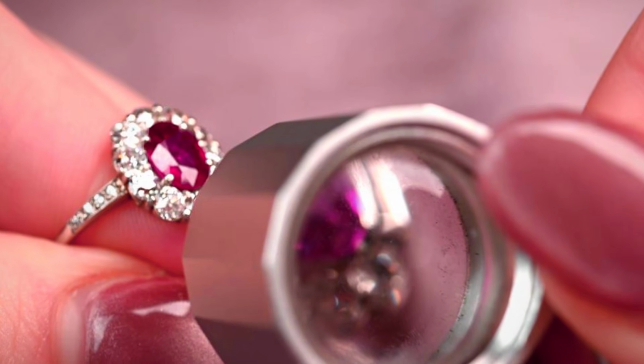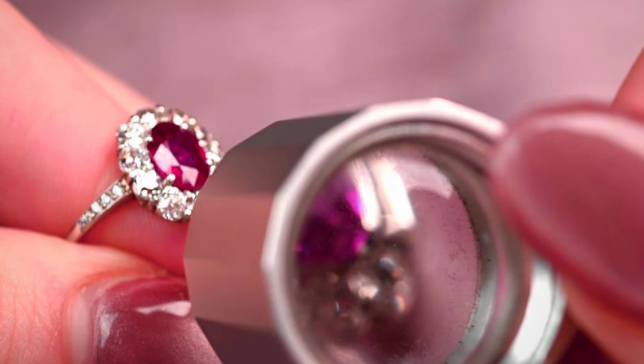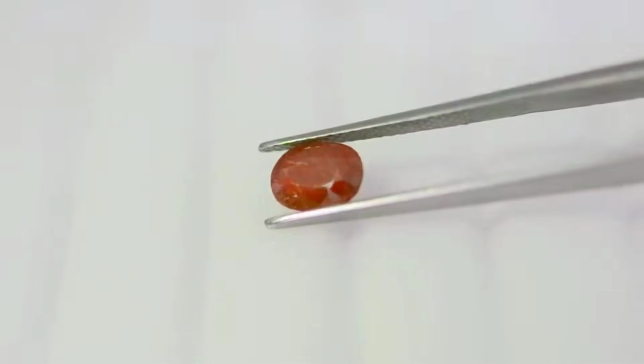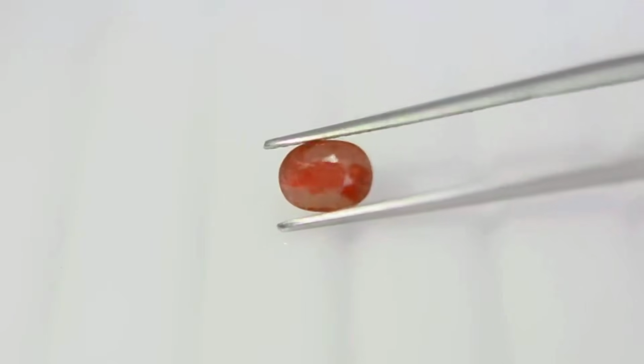But under a 10-power loupe, you will see blue or orange flashes from thin film interference at the glass-corundum boundary. Gas bubbles cluster at the fill edges like tiny trapped air pockets. The treatment is not permanent. Lemon juice dissolves it. Hot water eats it. An ultrasonic cleaner will leave you with a pitted, worthless mess.